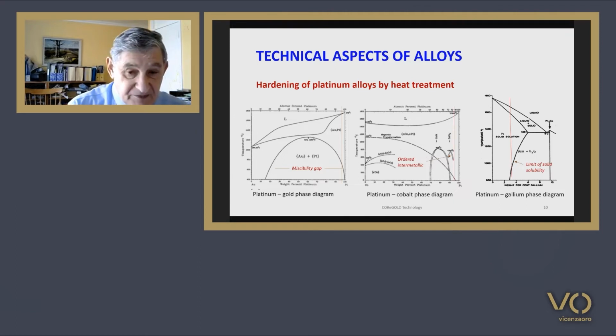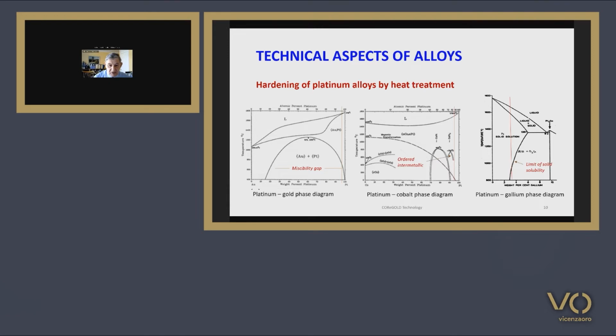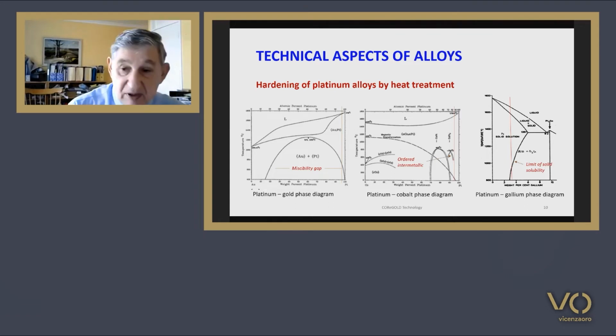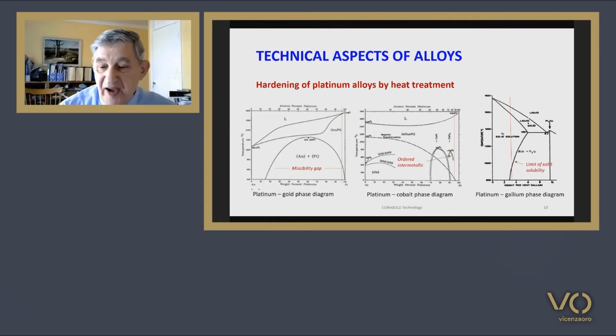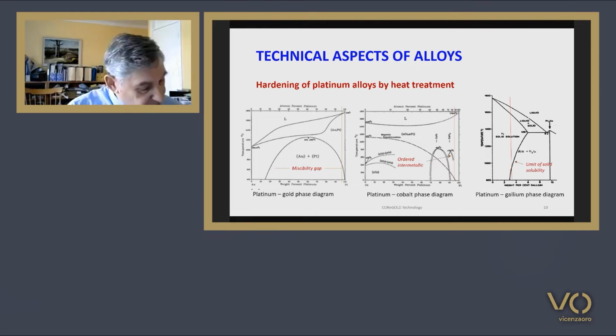The centre phase diagram, the platinum-cobalt phase diagram, and ordered Pt3Co that just about touches the 5% cobalt composition line marked in red on the slide, suggests that possibly there might be some slight hardening available by age hardening heat treatments. The use of gallium, as we can see in the phase diagram on the right-hand side, shows the 3.5% gallium composition intersecting the limit of solid solubility, again demonstrating how we can use age hardening treatments to harden gallium-containing alloys. Its use forms the basis of several heat-treatable alloys, as we noted in the table.